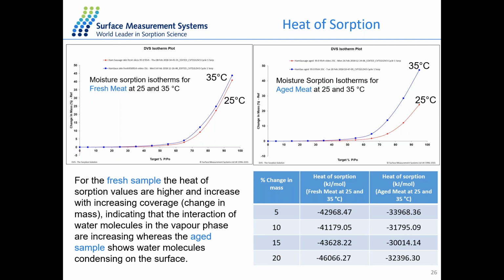So in fact, the probe molecule, in this case water, interacts with only the other water molecules, resulting in some condensation on the surface rather than interacting with the meat sample itself. So that's how we use the heat of sorption parameter to predict the behavior of fresh meat and aged meat samples.